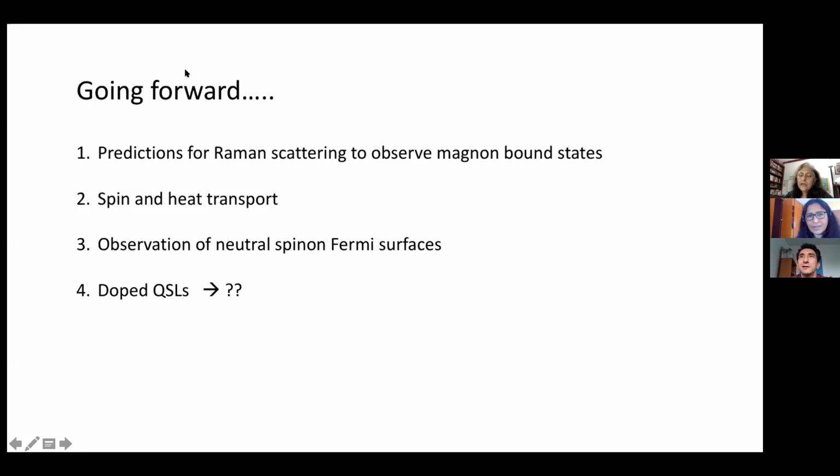So this interplay between Heisenberg, Kitaev, and the physics of Kitaev under field. Right. So I think it's important to try to get materials where, even if you can't get rid of the Heisenberg interaction, it can be small. So in ruthenium trichloride, the Kitaev interaction is about 80 Kelvin and the Heisenberg interaction is about 8 Kelvin.